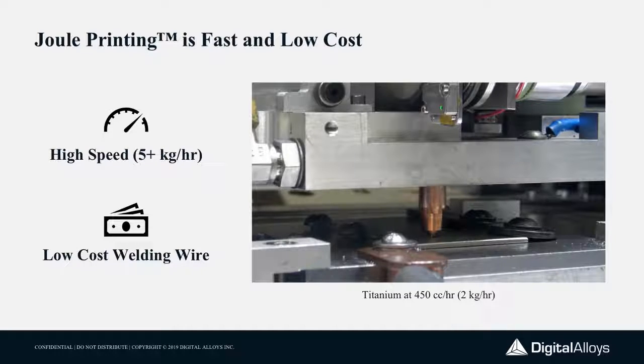And as you can see, we can move very quickly in depositing that bead. We're using roughly a millimeter wire. We're laying down a bead of metal that's about the same proportions as the wire. So we're printing with that wire size. We're printing titanium today. That video is at about 2 kilograms an hour. I'll show you another video, I think it's in here, where we're printing at about 4 kilograms an hour. We're printing steels and denser metals at 7-8 kilograms an hour. So we're really operating at the very fastest of metal printing speeds, but with an order of magnitude better resolution than what you could get out of these welding type processes.